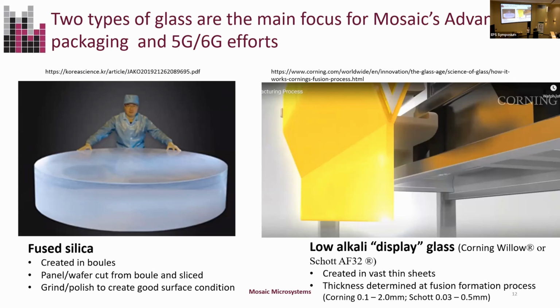Bottom line is that glass is compatible, certainly with the back end of the line. I'm not sure if people want to put it in with their silicon transistors, but back end of the line, very compatible with fabs. And once you take a piece of glass that's been cut into a wafer and put it on a silicon wafer, then as this glass moves through a fab, even the chucks only see the silicon that they're used to seeing. So there's no contamination there. And so these are the main types of glass that Mosaic has concentrated on so far. We're open to others, but this has been mostly it. And so the wafers over here have to be cut out of the boule and then sliced like a silicon wafer.